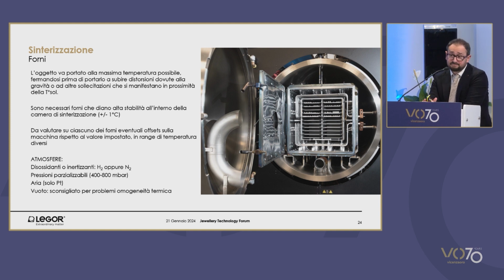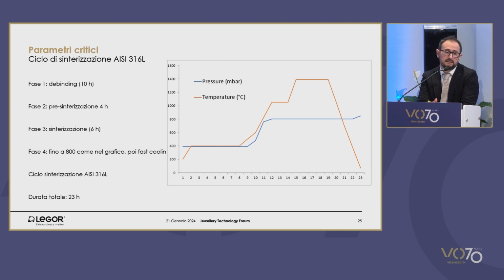For platinum, we have used an oven that uses air, since platinum has some highly desirable features, the very high temperature and the very strong oxygen inertia. Therefore, that high temperature allows me to work easily and eliminate the binder. Vacuum is not advised for sintering because it prevents heat homogeneity in the chamber, which is fundamental to guarantee that all items inside the chamber on the different trays are correctly heat treated.